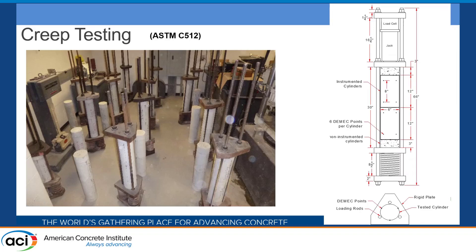Regarding the creep test, just showing you part of the setup. We did eight different mixtures for creep, while shrinkage was done on all 40, because we don't have enough frames to do 40 creep tests in our lab. We picked the eight with the highest paste content as the most critical ones. Every frame also has cylinders outside to measure drying shrinkage, so we can isolate the creep strain from the shrinkage.